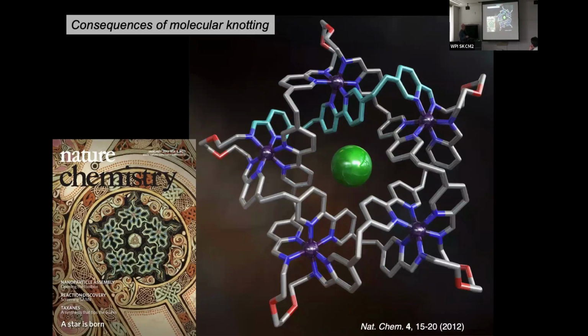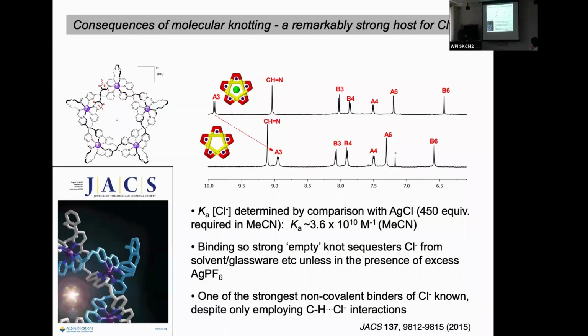They're held very tightly by the CH hydrogen bonding interactions of these bipy rings. These are very electron deficient because the metal ion is drawing the electron density away from them. So this forms very strong CH to chloride hydrogen bonding. And we can see that in the NMR spectra. If you pull out the chloride ion by adding silver salts, then these protons that are hydrogen bonding to the chloride ion, they shift nearly 1 ppm in the NMR spectra between the empty cavity and the chloride cavity knot.